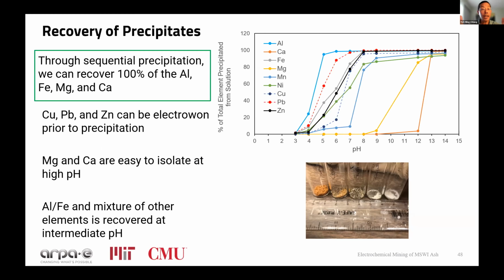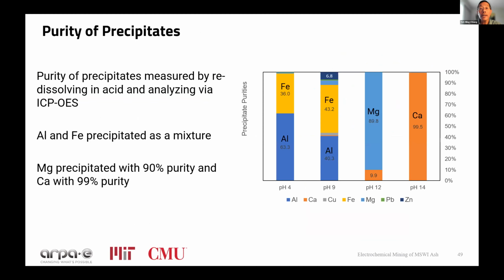We just precipitated everything. And the main point is, if you go first to the high pH, it's easy to separate out calcium that comes out at the highest pH. Everything else is already precipitated by then, if you're starting from low going to high. And before that, you can get the magnesium first. And then you have a group, a cluster of others, that are going to take more work to separate, right? So you look at the purity of these, and this shows that, as you vary pH from 4, 9, 12, 14, the calcium and the magnesium are pretty pure. And now you have iron and aluminum and a few others mixed in there, right? So that requires some more precision than what we've used so far. And we believe that there are chemical engineering approaches that can start to parse those as well, right?